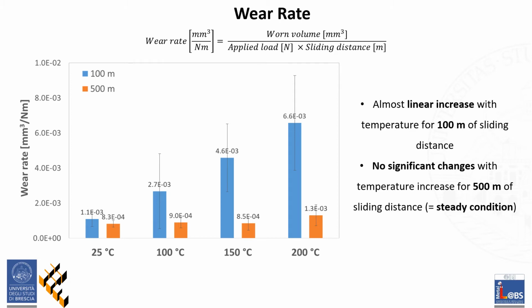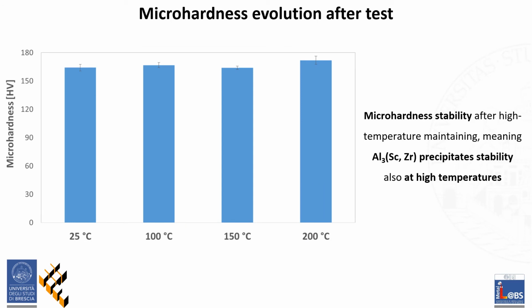In order to understand wear rate changes, microhardness was evaluated after pin-on-disc tests. In fact, microhardness test allows the identification of possible microstructural variation after the 6–7 hours of high temperature maintaining during the pin-on-disc tests. As a result, a great stability of microhardness can be observed as the testing temperature increases, as can be seen in the plot. This fact reveals Scalmalloy precipitate stabilities also at high temperature.